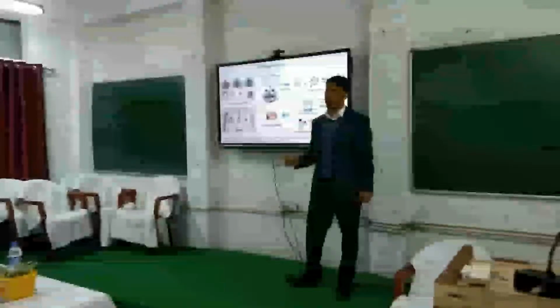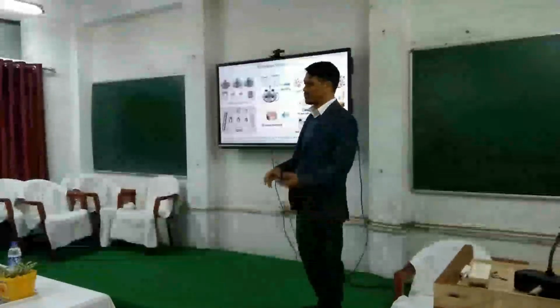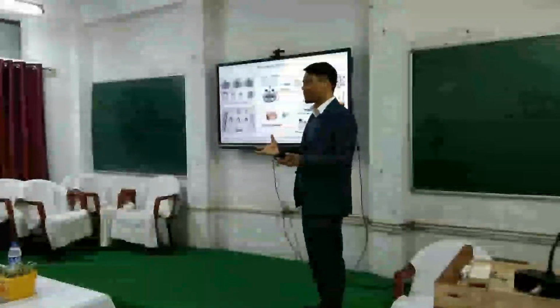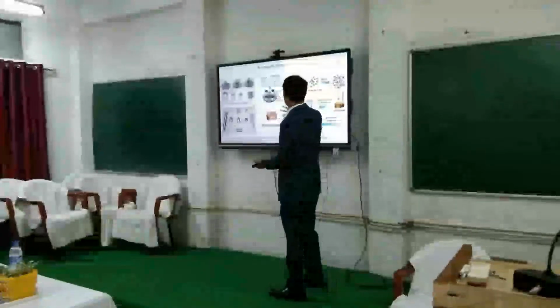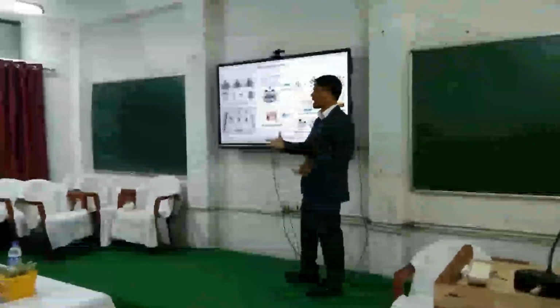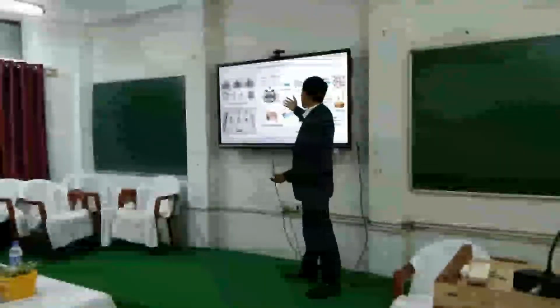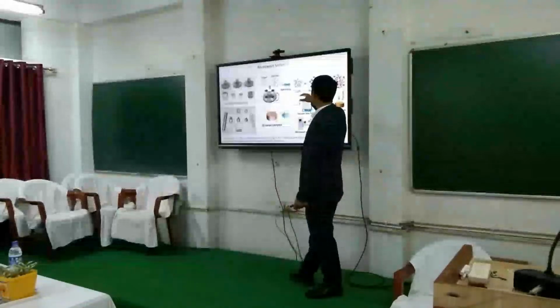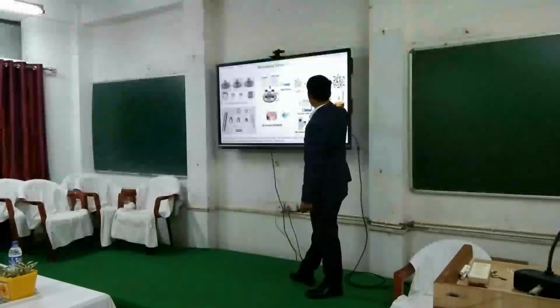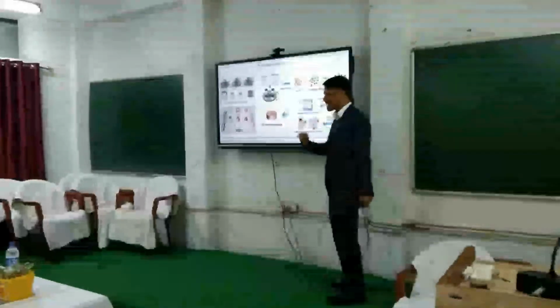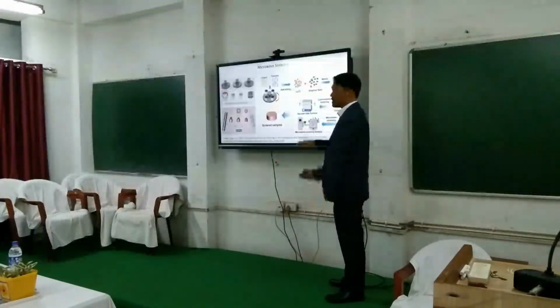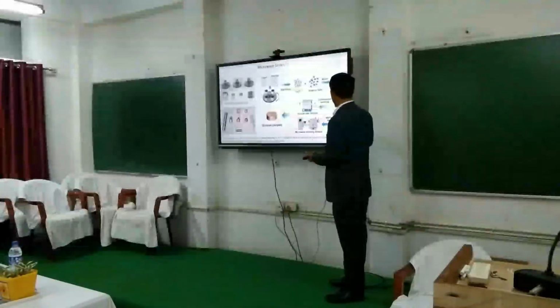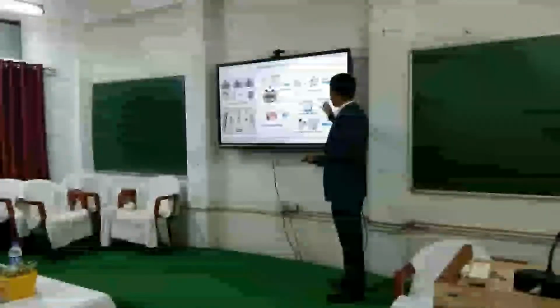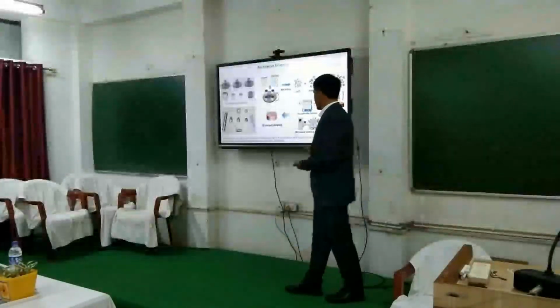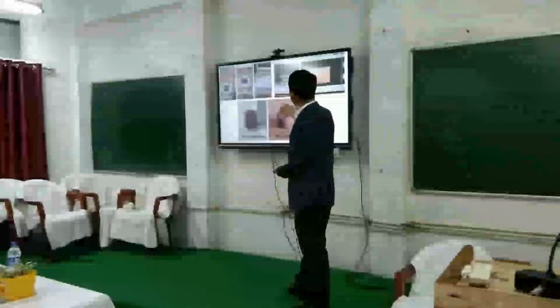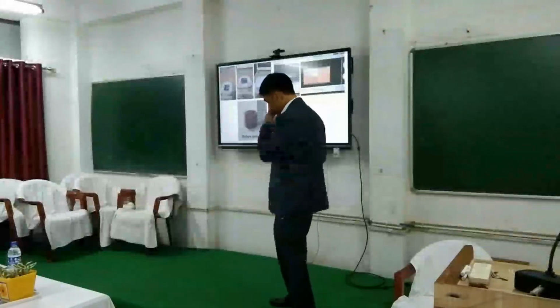near net shaped manufactured parts. Earlier they used to do this by powder metallurgy and conventional sintering, but nowadays we can also use microwave sintering. So we have powders, any type of powder. Here, as an example, there is copper and titanium, and then we mix the powders together to form these green samples, which are basically formed by some compression or pressing, and then they can be either conventionally sintered or microwave sintered. This is some results which we have done recently.